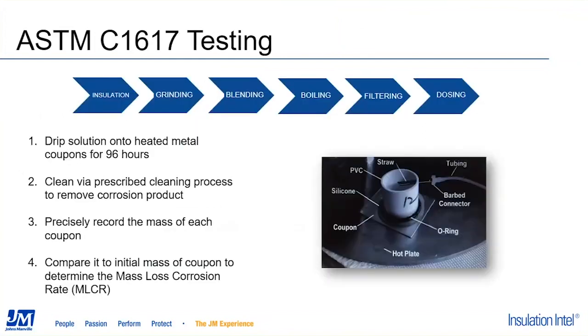Let's start with the ASTM C1617 test protocol. One of the big advantages of this as compared to some prior test protocols is that it was designed specifically to look at corrosion on carbon steel, whereas many of the prior standards were focused on stainless steel. The procedure for performing this test is to take the insulation material, grind it into a powder, or shred it as finely as you can, mix it with DI water, blend it together, then filter out the remaining solids so that all you have left is the liquid with any compounds or materials that may have leached out of the insulation itself that could contribute to corrosion.